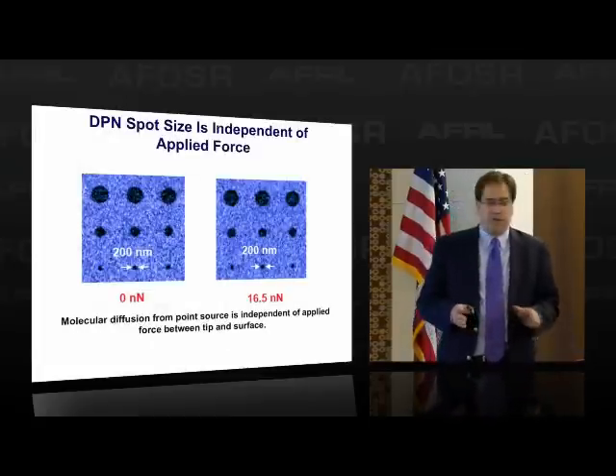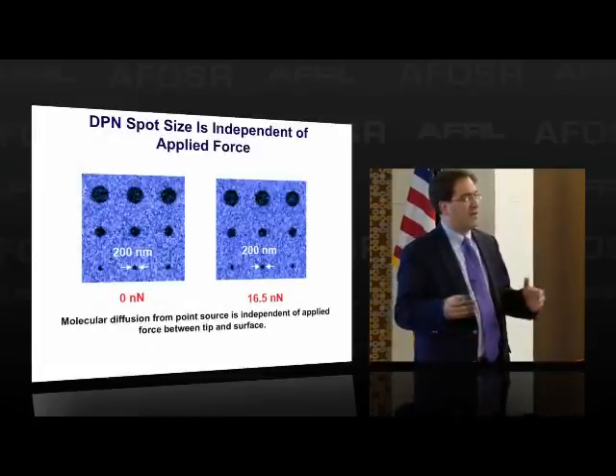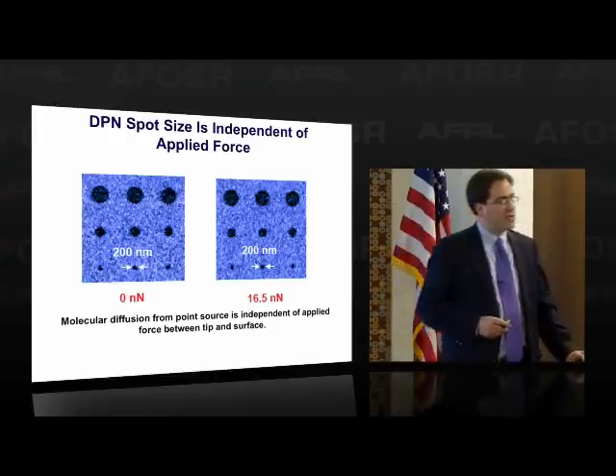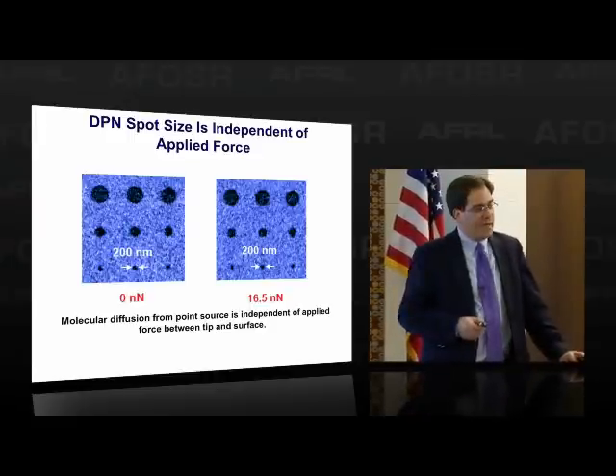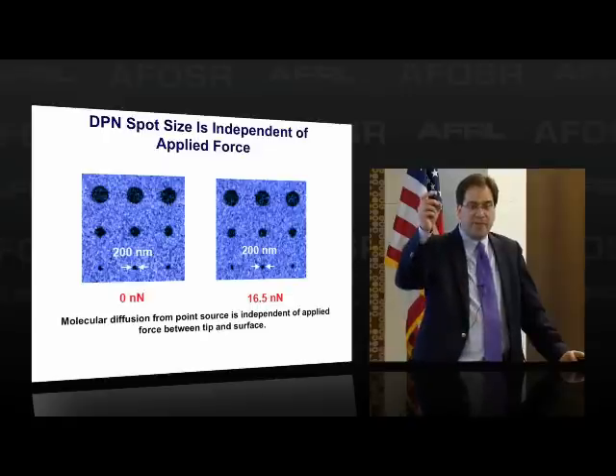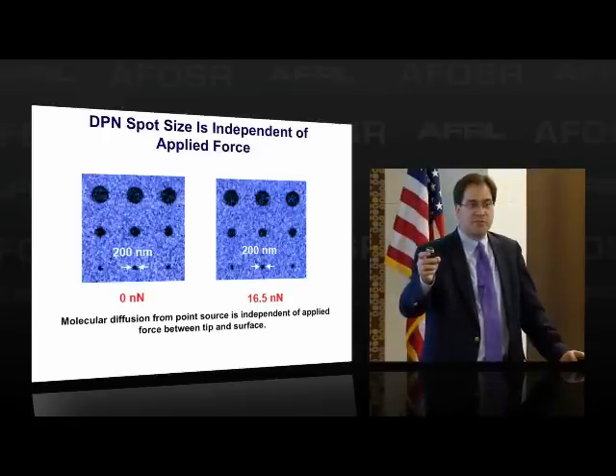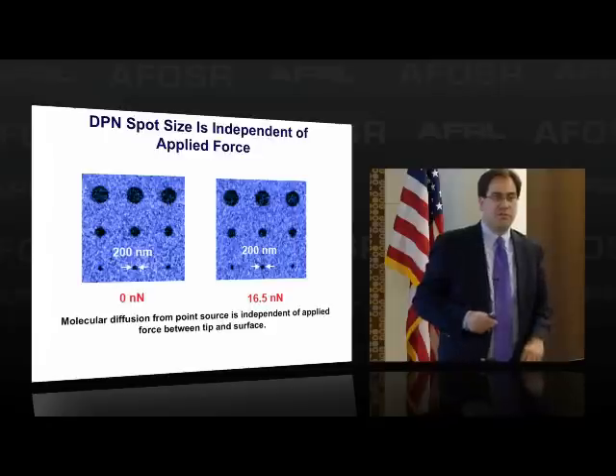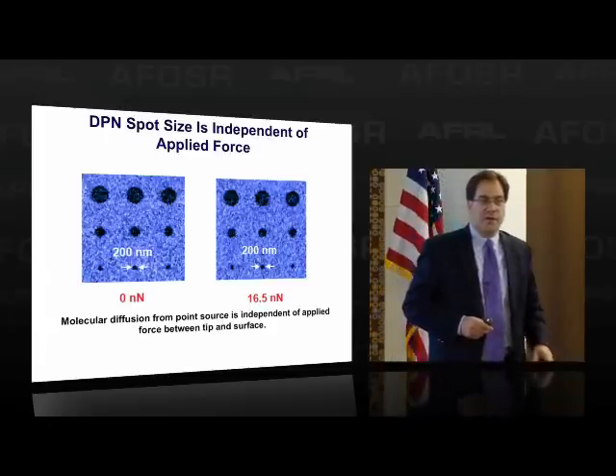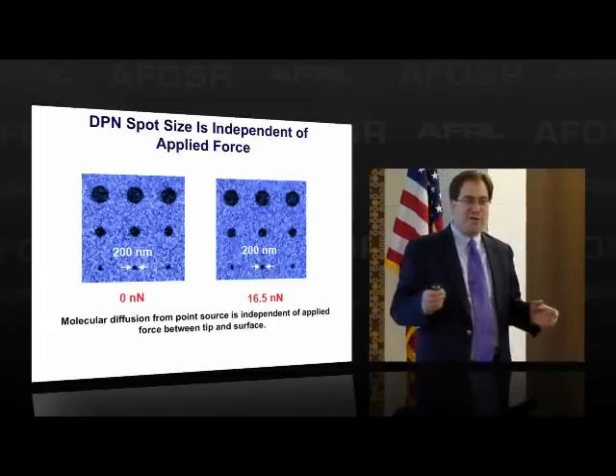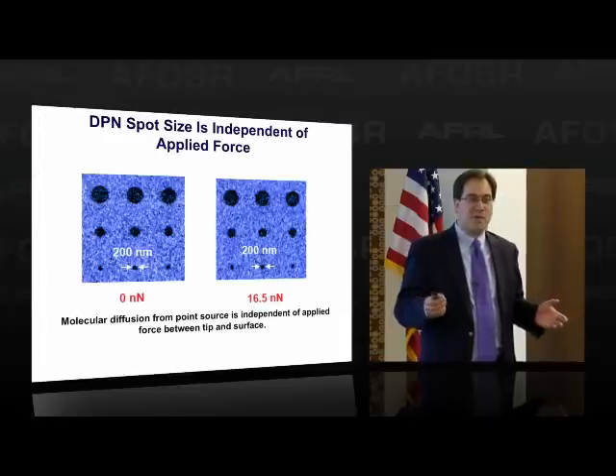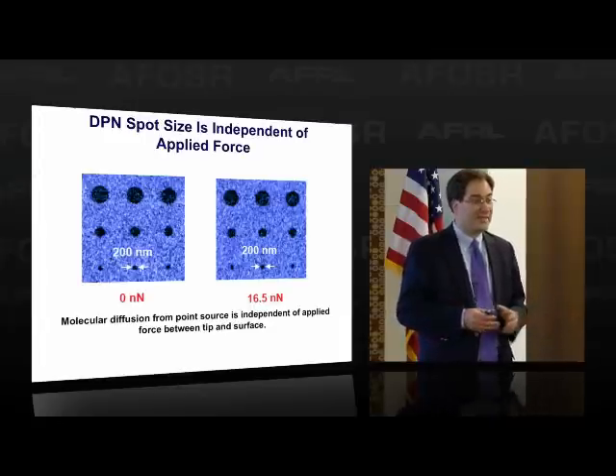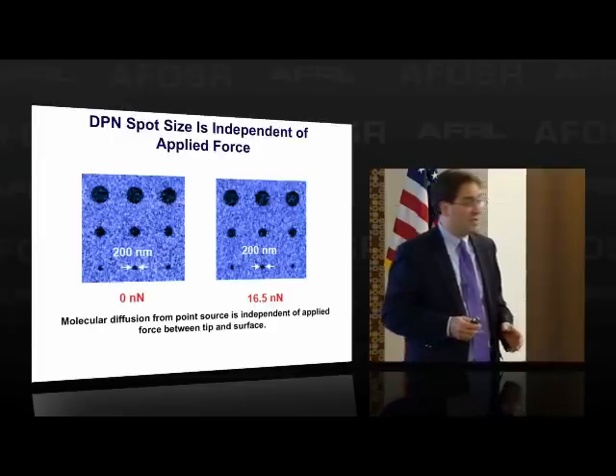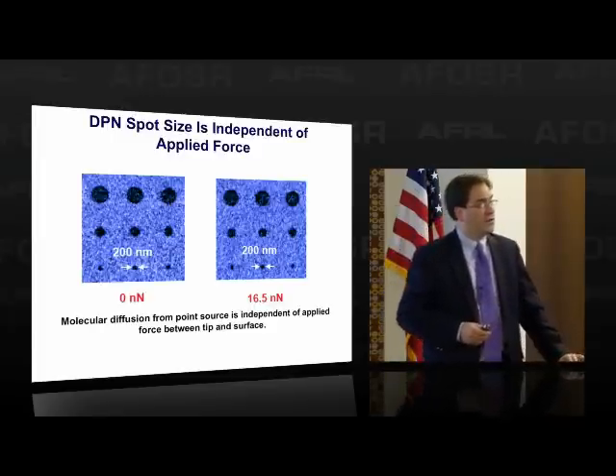Okay, so let me tell you one of the big problems associated with DiP-Pen. So I'm talking about a lot of the strengths. Problems and also potential advantages. One is that if I want to make big structures, in addition to small structures, it's actually pretty difficult to do in a DiP-Pen experiment. Because what happens is you bring the tip down in contact with the surface. Molecules begin to diffuse from the tip to the surface and anchor onto the substrate. And again, if you're working on a small length scale, that's a reasonably fast process. But if I want to make micron or many micron type structures, it takes a long time for that diffusion process to take place and for you to get stable structures on the surface.